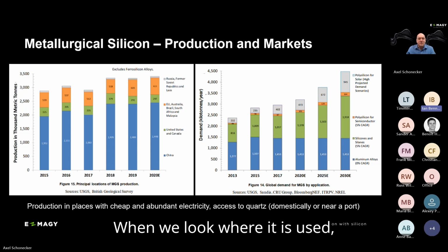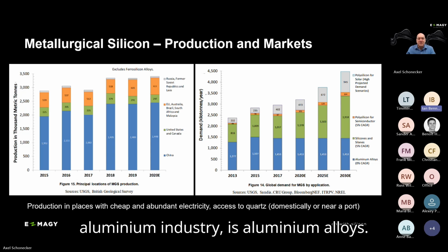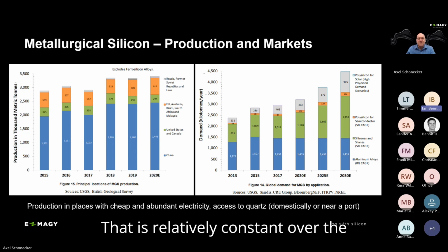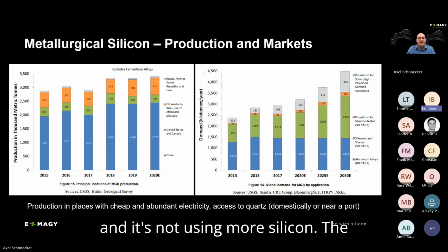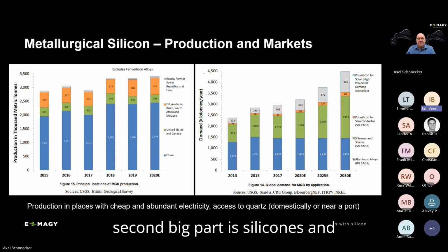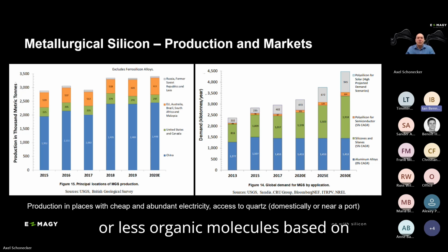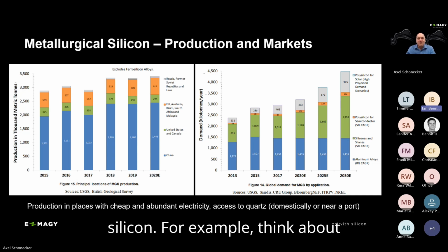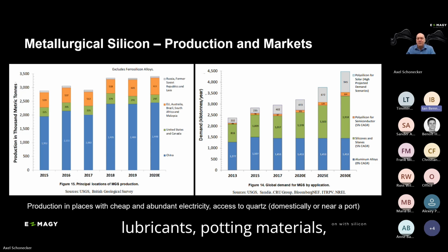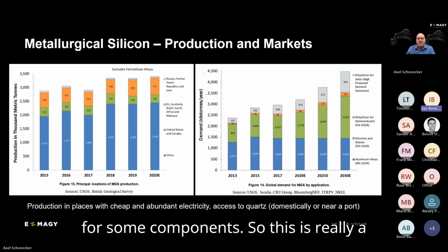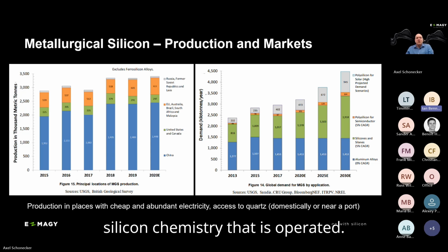When we look where it is used, so the total of the metallurgical grade silicon in 2025, for example, you see a major part is going to the aluminum industry as aluminum alloys. That is relatively constant over the years. So we don't need more aluminum and it's not using more silicon. The second big part is silicones and silanes that are more or less organic molecules based on silicon. For example, think about lubricants, potting materials, sealants. It's also used in the building industry for some components. So this is really a silicon chemistry that is operated.